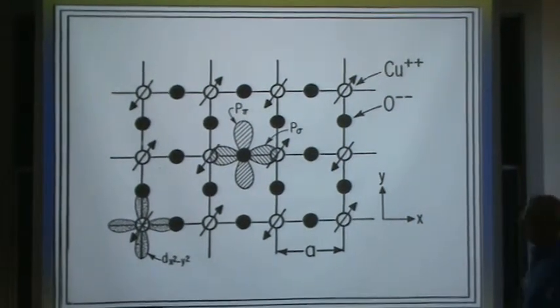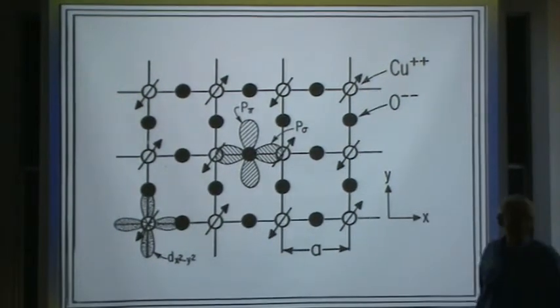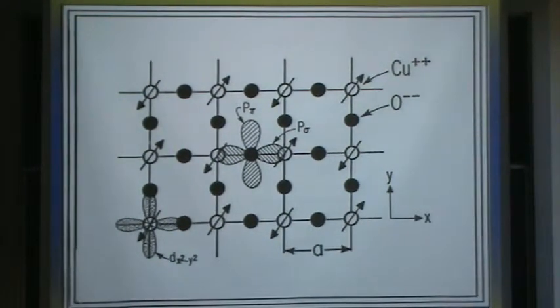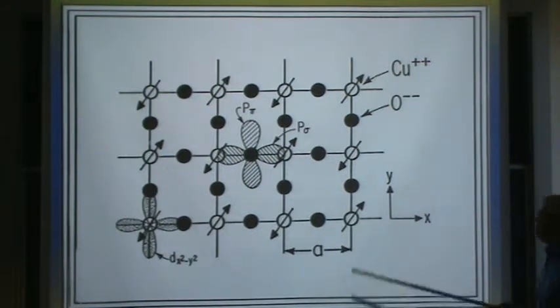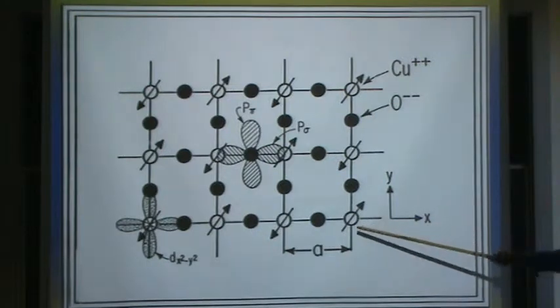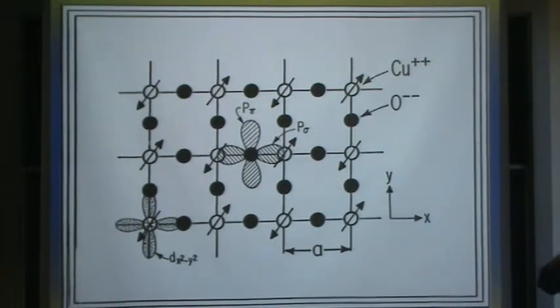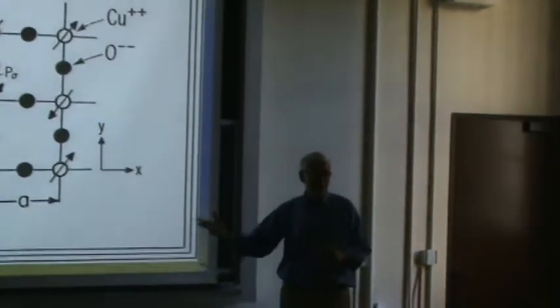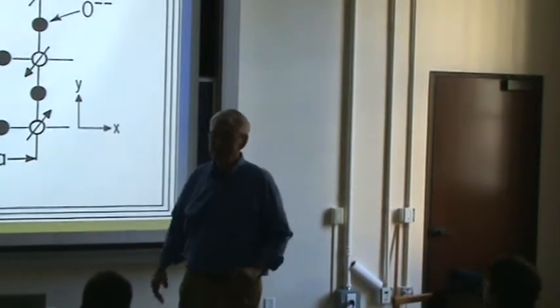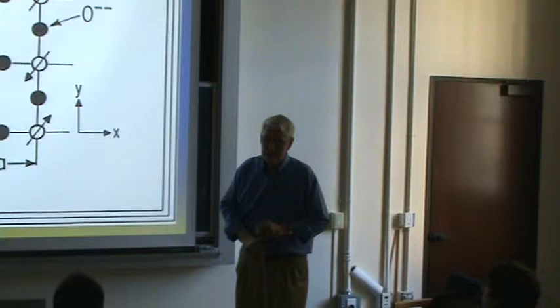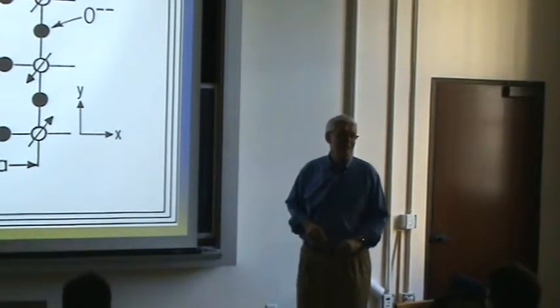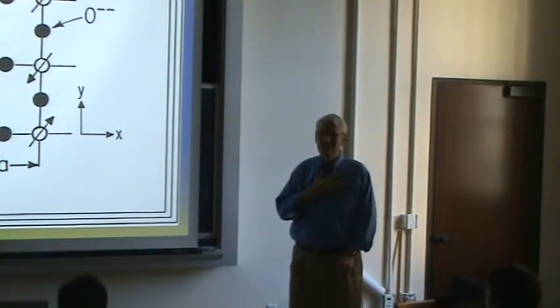The reason it's disturbing is that the copper has a hole, and that hole carries the spin. So this would suggest that the copper oxide, which carries the superconductivity, is actually a concentrated lattice of spins. But everything you know about superconductivity says you can't have spins, because the spins break the Cooper pairs, and therefore the material will not be a superconductor. At first, people figured this out pretty quickly, and therefore the first 2 years of publications were in complete denial.